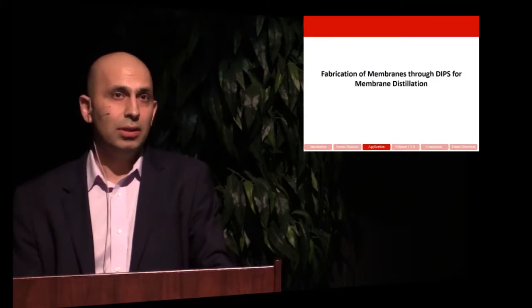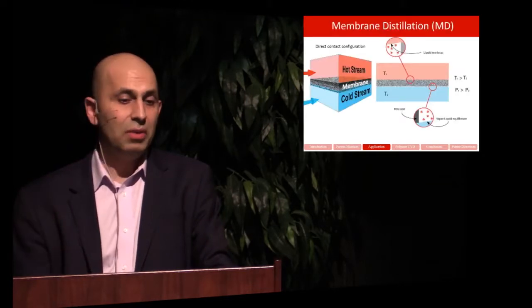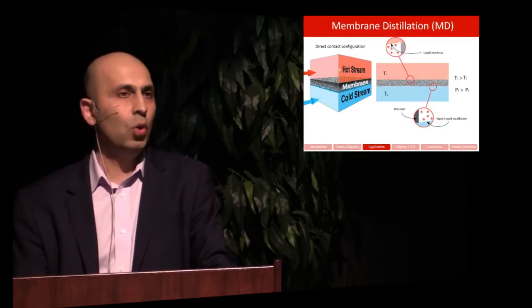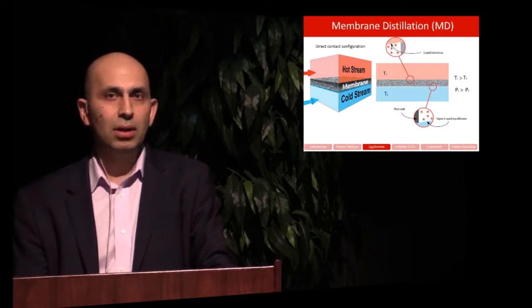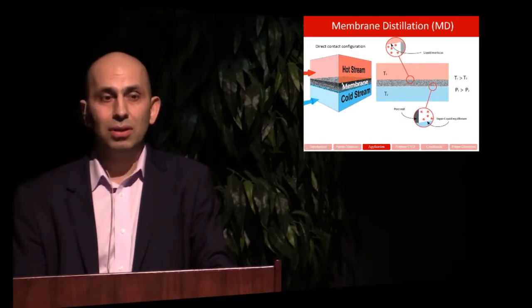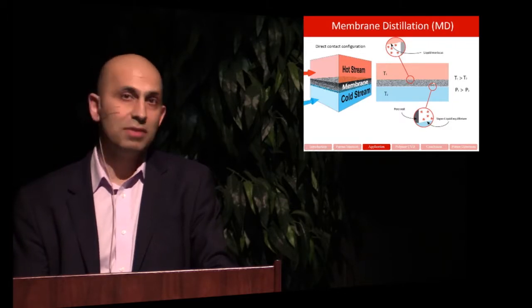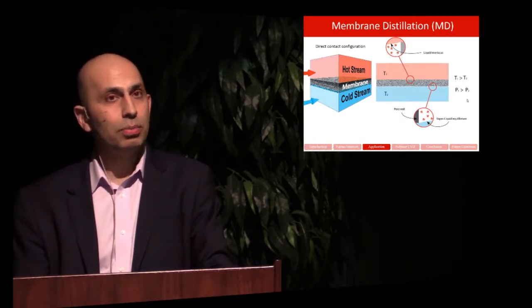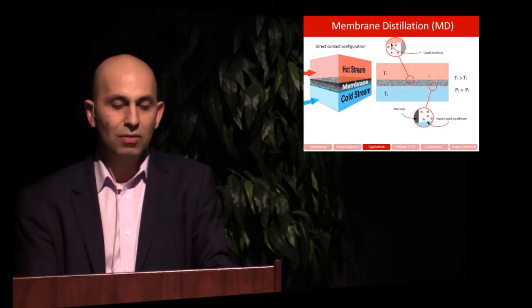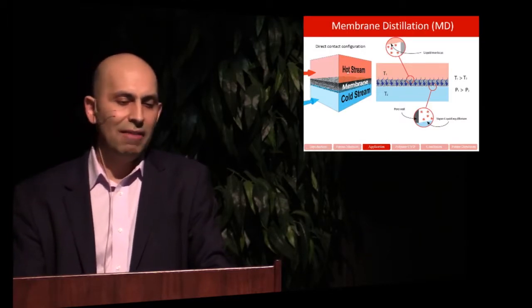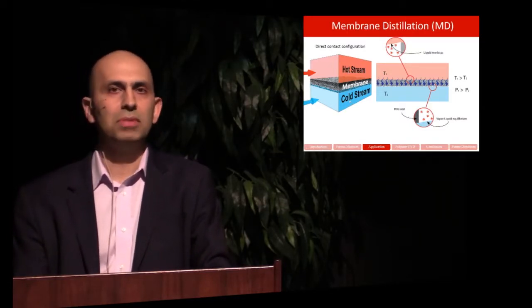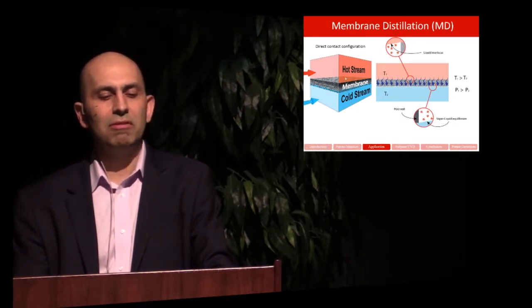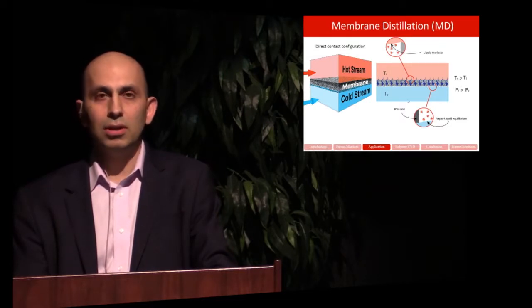So there's a process called membrane distillation. As the name suggests, it's a distillation that has been assisted by a membrane or a porous barrier. The way it works is pretty simple. You have hot water on one side and cold water on the other side. This barrier, or the membrane, does not interact with water well, so we call it hydrophobic. But it is porous, so water vapor can pass through. If you create a temperature gradient on the two sides of this barrier, that temperature gradient is translated to a pressure difference, and as a result, you can pass the solvent through this barrier. Let's say we have a brine, or salty water, here, and on the other side we have distilled water. We can keep increasing the flow of water vapor from the salty side to the clean water.